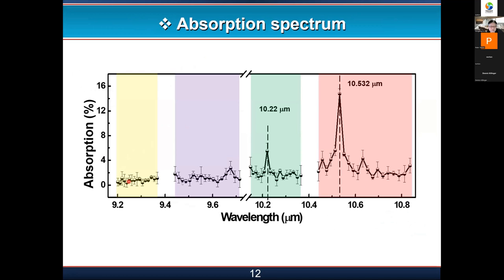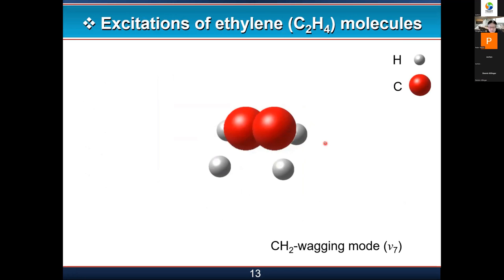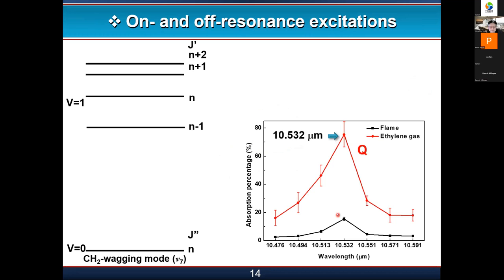And this is the absorption spectrum of the ethylene molecules, and it has the vibration mode. Unfortunately, the animation doesn't work well here. Basically, the 2 carbon atoms and 4 hydrogen atoms vibrate in opposite directions, and they call it the wagging mode. We can see the absorption, corresponding to the ground state to the excited state, at 10.532 micrometer, and we have this resonance peak.